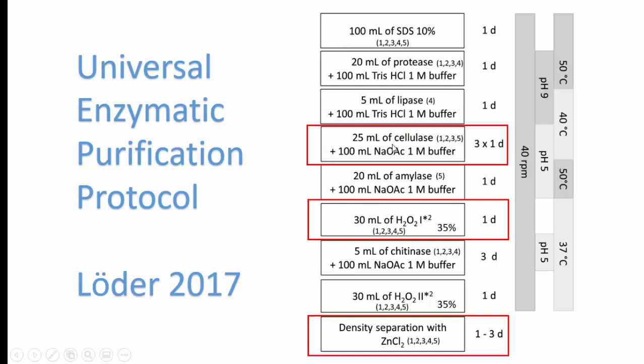And so these 3 steps we took, and we chose to improve upon them, because looking at here, look at the amount of time it was required to do this analysis. It ranged from well over a week up to 15 days to prepare all these steps. Keep in mind, each one of these steps you're adding something to the sample. It's exposed to your lab environment. So if contamination is ubiquitous, if it's everywhere, you're going to contaminate that sample at every step along the way.